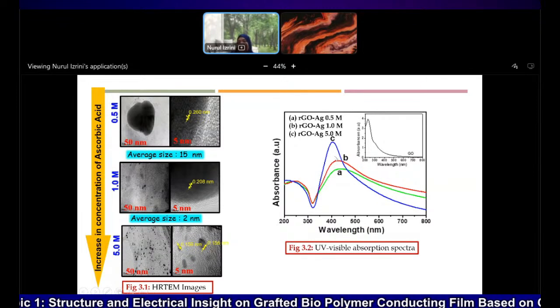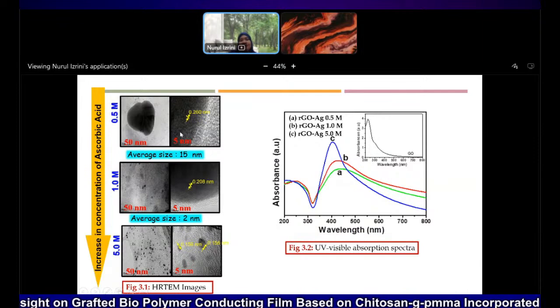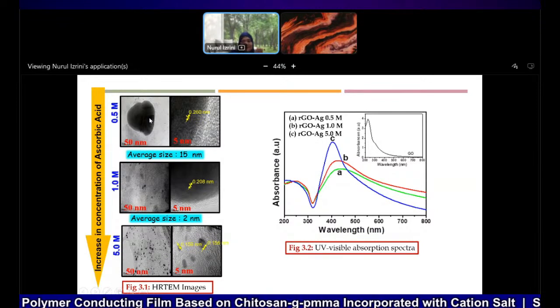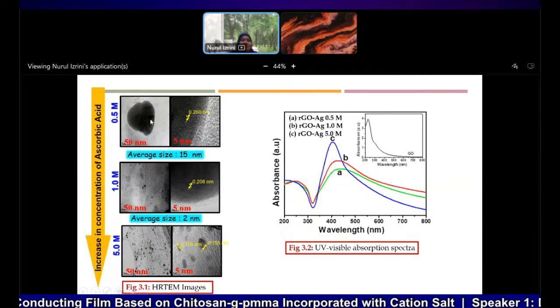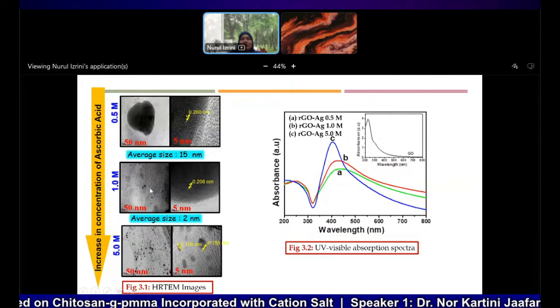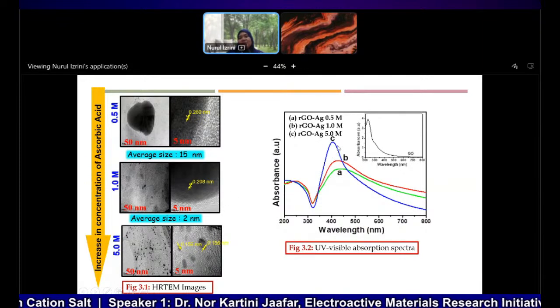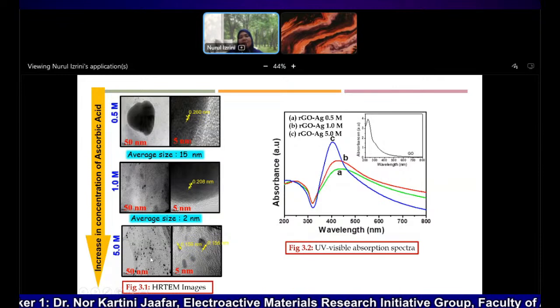This result also relates to the TEM. When we ran the TEM image, for the 0.5 molar sample we cannot see the formation yet because of combinations - slightly spherical shapes with agglomerates. For 1 molar, we also cannot see very spherical shapes of nanoparticles. That's why we chose 5 molar as the best concentration, which also correlates with the UV-Vis. So based on UV-Vis and TEM, it shows very good distribution of nanoparticles.